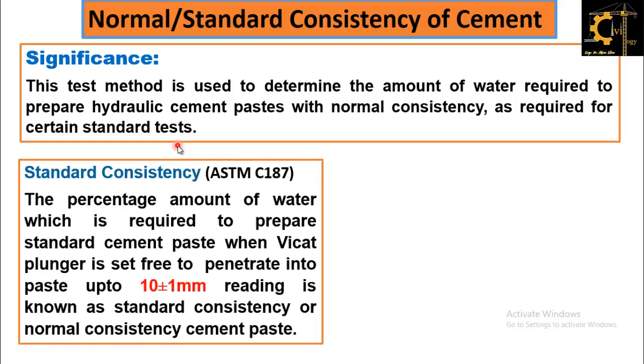paste. Now, according to ASTM standard C187, it is defined as the percentage amount of water which is required to prepare standard cement paste when the Vicat plunger is set free to penetrate into the paste up to 10 plus or minus 1 millimeters reading. This is known as standard consistency or normal consistency of cement. It is important to note that this value is 10 plus or minus 1 millimeter, that is, it ranges from 9 millimeters to 11 millimeters.